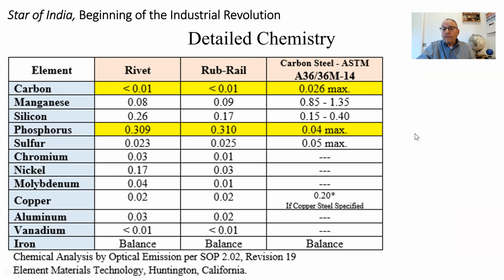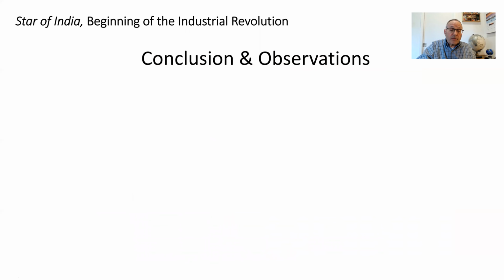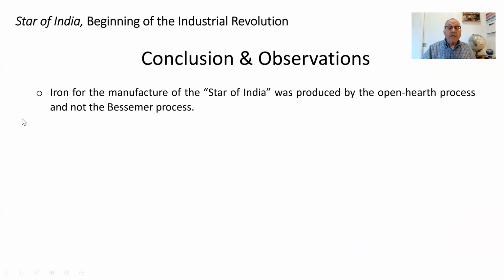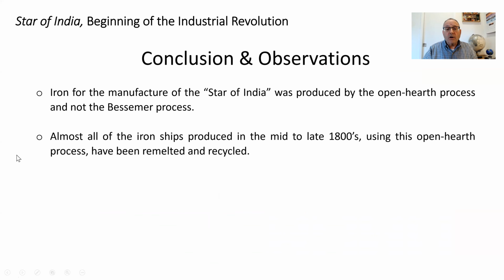So what can we conclude from all of this? Well, there's a couple things that we can conclude. One, that the iron for the manufacture of the Star of India was produced by the open hearth process and not the Bessemer process. So that was pretty clear by the amount of phosphorus that we saw in it. Almost all of the iron hull ships that were produced in the late 1800s using this open hearth process have either been recycled or remelted at this point. Most of them have been recycled and reused. So very few of them are available or still afloat, still around.